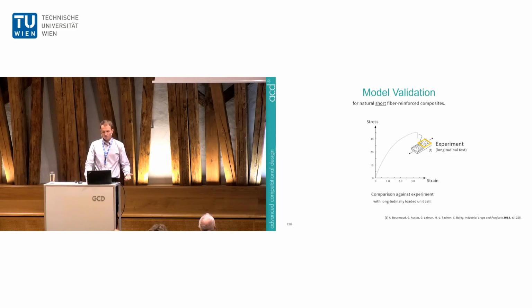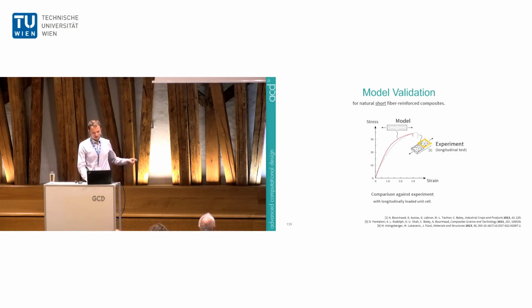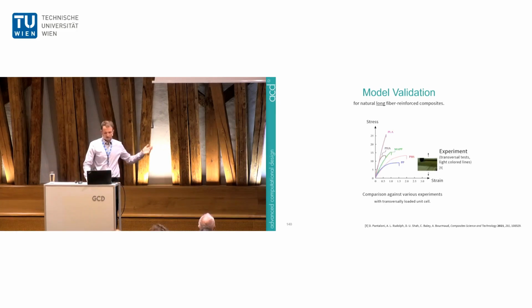And of course, we need to validate our model by comparing our predictions to real experiments. Here we have a stress strain curve, which is quite similar to the load displacement curve shown before, for example with short aligned fibers pulled in longitudinal direction. And as you can see, our model with the perfectly aligned fibers matches the experiment pretty well if pulled in just this direction. We can do a quite similar validation with long fiber reinforced composites. In this case, there are 5 experiments with different materials shown, while pulling them apart in transversal direction. And here, with these matching color pairs, you can see how our model matches the real-world experiments.